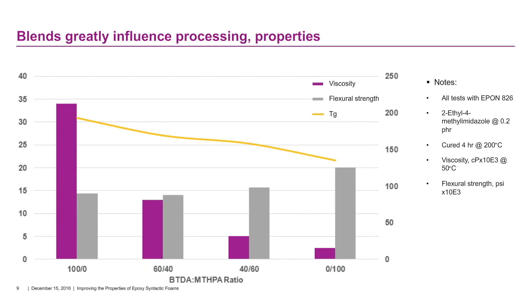And in doing so, then you can go back and fine-tune your mix of dianhydride and monoanhydride. The other thing to consider is that when you do put these blends together, there is a critical amount of dianhydride which is required in order to affect the change in properties that you're looking for. So if you decide to add only a little bit because you want a very easy to handle processable mix, you may not even be getting the benefits that you're looking for. So there are many trade-offs, and it makes the blend composition that much more complex.